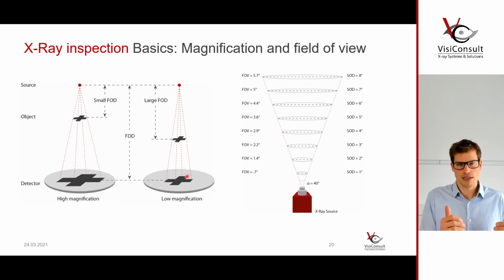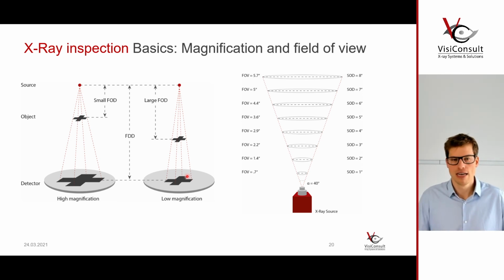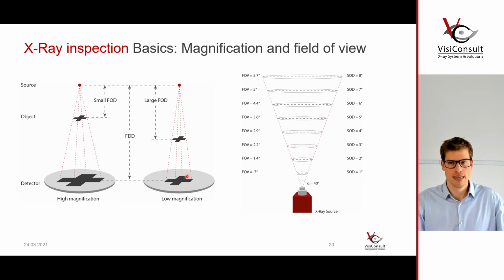If you want to achieve a defect detectability of 30 micron, you need to have a scan resolution of roughly 10 micron to safely detect the defects. And that means you have to magnify by factor 10, which limits your active area to 4 by 4 centimeters, which means the part that you scan is absolutely tiny. And this is what you have to keep in mind. When you define your defect detectability criteria and your quality inspection criteria, keep in mind if it's very high, then your scannable part can be very, very small only. And this might be an issue. So there is a trade-off and it has to be addressed early.